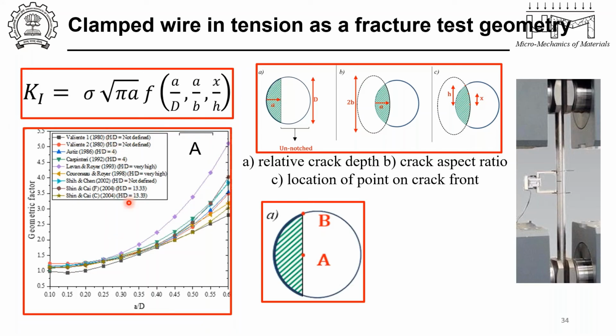So we collated the geometric factor solutions from various authors right from the 1980s. Some of them are not very well defining the geometric conditions, and their software doesn't allow them to refine the mesh a lot, so their solutions may be slightly off. But even among the recent ones, we saw wide variations in the geometric factor. So we were perplexed, and we looked at what the differences were, and we saw that again the aspect ratio of the wire, the H/D ratio, is different for each of these authors. Some of them have not defined it, but some of them who have defined take up different values. But as you can see, in the geometric factor calculation, they don't take that into consideration at all.